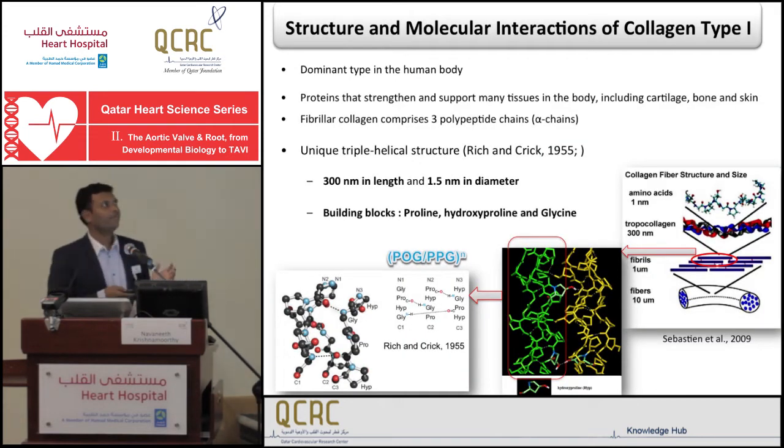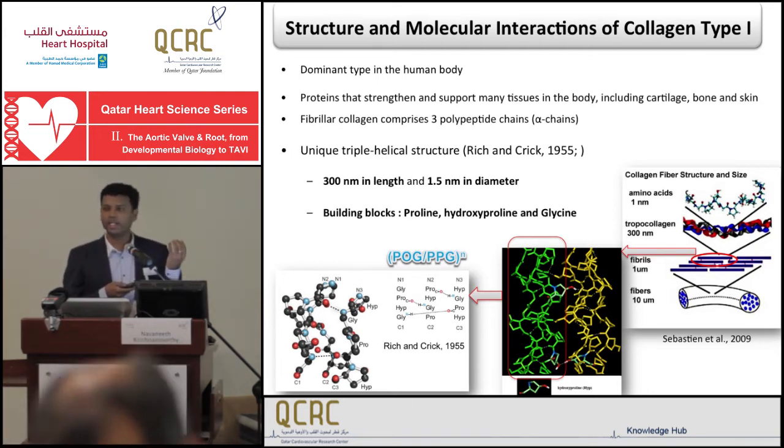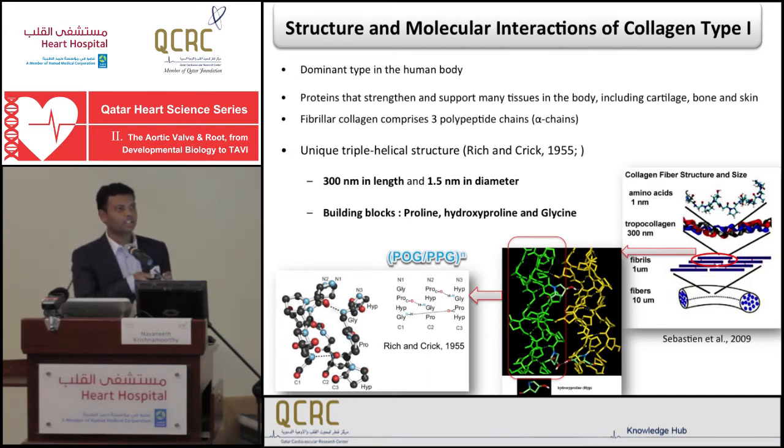Before going into detail, we should look at the structure of collagen, because it has so much information inside. It looks like the nanofiber you see on the surface of the extracellular matrix, but when you go deep and see the molecular structures, they are arranged in a proper way. This is the triple helix I am talking about, the collagen mimetic peptides. When they are arranged in a staggered manner, they produce these nanofibers. These collagen triple helixes are basically constructed with three important repetitive residues: proline, hydroxyproline, and glycine. These are the building blocks for this collagen structure.